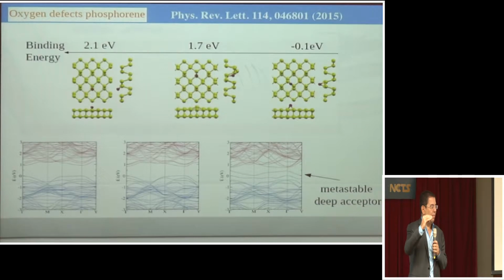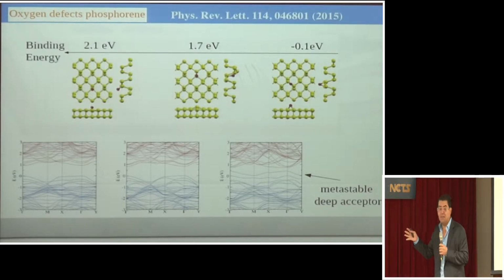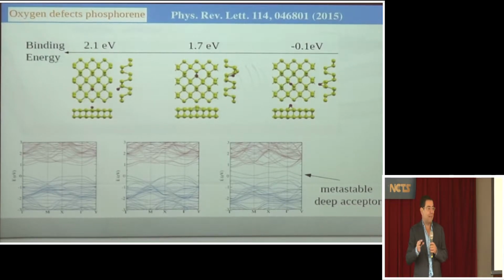So the type of defect that you find in the electronic structure depends very much on the position of the oxygen in the crystal structure. So a lot of time is spent understanding oxygen in these materials, but this should be no surprise for people working, for instance, in the traditional semiconductor industry. The semiconductor industry spends a lot of time and a lot of money to understand defects in silicon, in gallium arsenide. So there is nothing surprising about this.